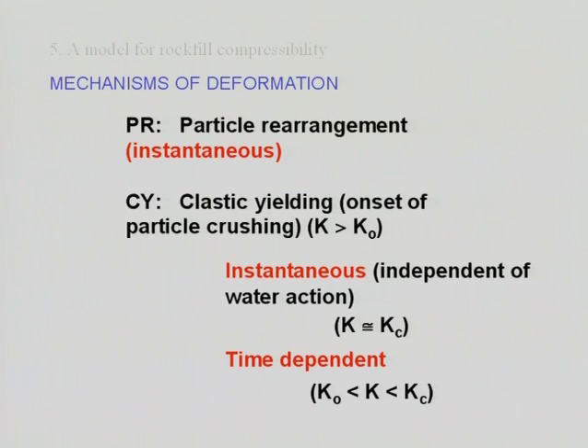Now, from the point of view of the mechanism of deformation, we may synthesize those results a little bit. We have particle rearrangement. This tends to be instantaneous. And then we have cracking, failure of the particles. Whenever we have some particle crushing, then, from a conceptual model, the contact points are in a region in which the stress intensity factor is higher than this threshold value. And again, here we may distinguish instantaneous. The instantaneous deformation will come if we reach the toughness, but most of the contacts will be under a time-dependent regime, and in our underlying conceptual model, on each of those contacts we will have a stress intensity factor which is in between the toughness and this threshold value.